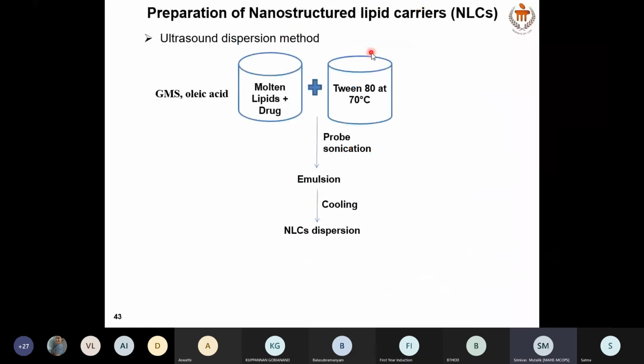The nanostructured lipid carriers were prepared by ultrasound dispersion method. So GMS, glyceryl monostearate, and oleic acid were used as the lipidic phase. NLCs contain solid lipid as well as liquid lipid. So this is solid lipid and oleic acid is liquid lipid. Then they were melted, drug was dispersed, and in another beaker we heated the aqueous solution of Tween 80. So both were mixed and probe sonicated. Then the emulsion was cooled, and finally we got nanostructured lipid carriers where the nanoparticles were collected by centrifugation.